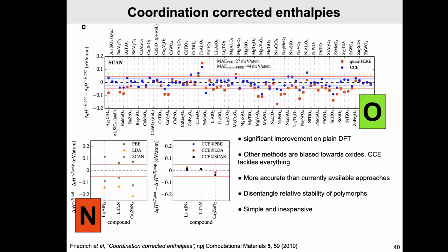Okay. We have not tested the magnetic disorder, but we have tested the effect of disorder on the phonons. The change of the vibrational free energy with respect to the disorder, and we found that it was negligible. This is for the vibration. We have not tested the magnetic disorder yet. Which means that it is possible that we might have a diamagnetic material that is high entropy diamagnetic. I don't know. We have not tested. So far, I can only tell you that the vibrational one is negligible.